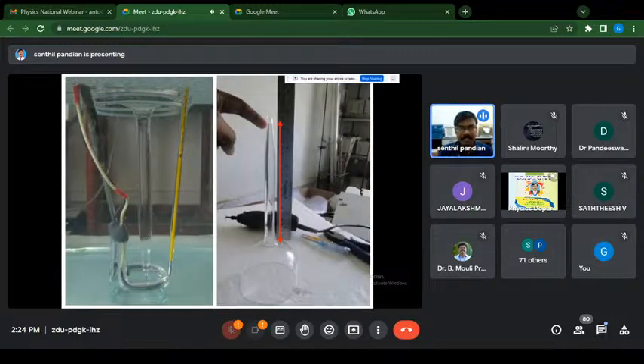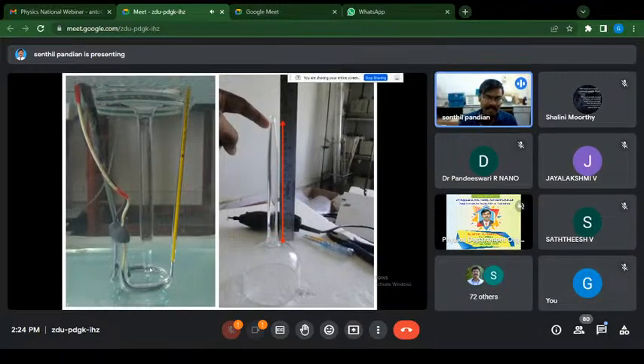Then we have grown a lot of organic, inorganic, semi-organic, positive soluble and negative soluble single crystals by this SR method. And how to harvest the crystal from the glass sample. So this is the 20 centimeter long TGS, triglycine sulfate crystal along its polar B direction. So we have maintained one temperature at the bottom portion and a higher temperature at the top portion. It was 38 degrees Celsius.